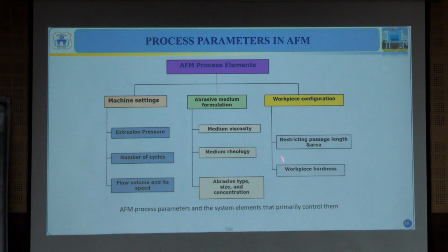Next, abrasive type, size and concentration. This is the type of particle you are choosing, the size of the particle and the concentration. You can choose silicon carbide or any other abrasive particle, and size and concentration also matter. If the abrasive size increases, then your material removal increases, whereas your surface finish deteriorates, if you use coarse grains. If you use fine grains, the surface finish will improve, whereas MRR will be low. So there is an impact of abrasive size and concentration.